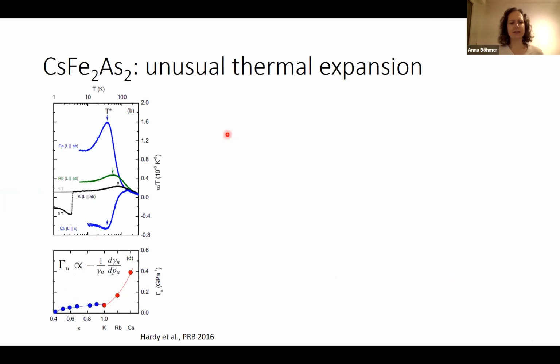And there is another interesting property of this. It has not only a huge Sommerfeld coefficient, it also has a huge Grüneisen ratio of the Sommerfeld coefficient. We just talked about Grüneisen ratios, which is here the in-plane pressure derivative of the Sommerfeld coefficient. And as a consequence, or almost analogous to this, the thermal expansivity, the alpha coefficient here, is huge in the cesium compound.